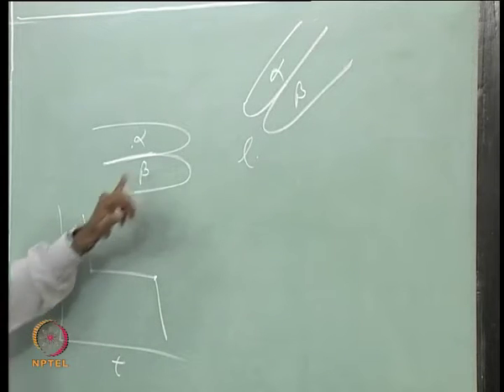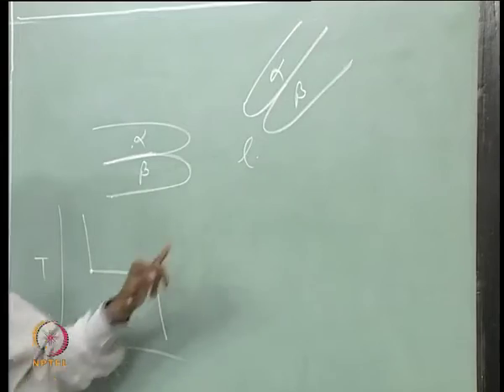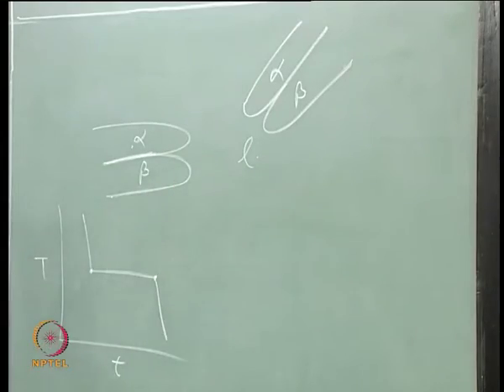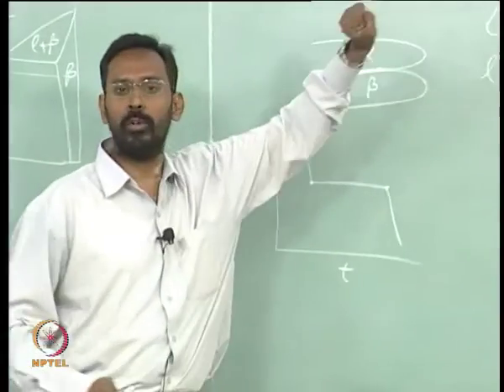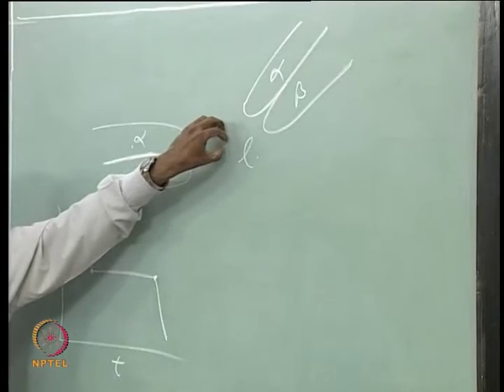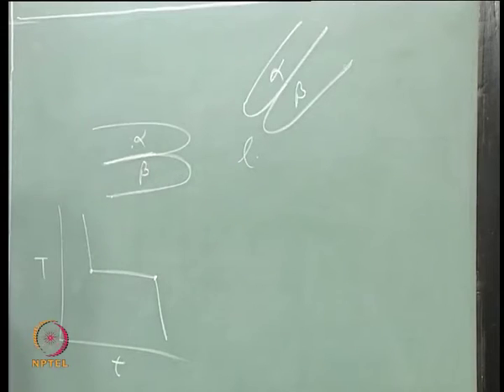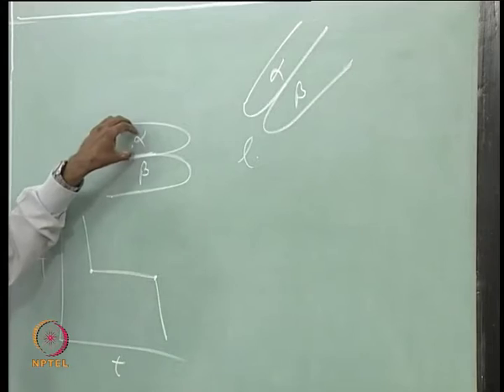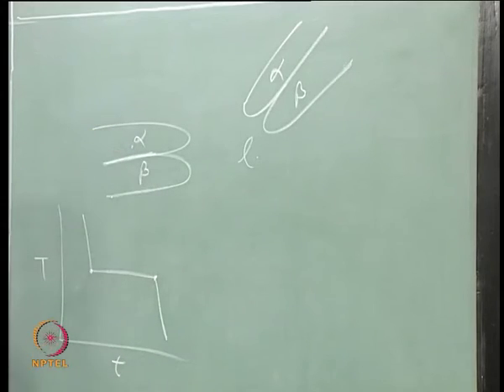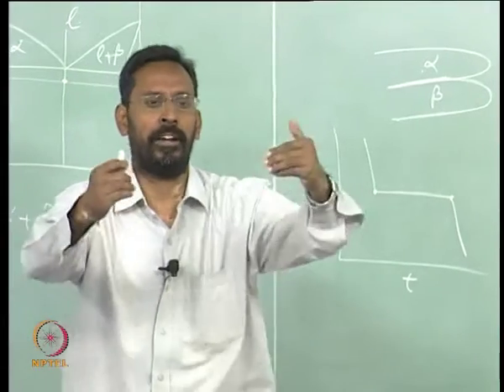Basically this alpha-beta grows at the expense of the liquid. That means for alpha and beta to grow together, you need liquid to supply more A atoms to alpha and more B atoms to beta. This is a very tricky problem. How is it that the liquid in front of it is selectively able to supply more A atoms to alpha and more B atoms to beta, such that they grow together?